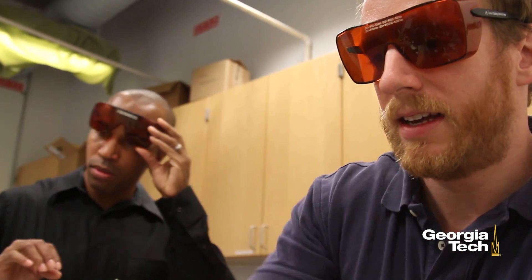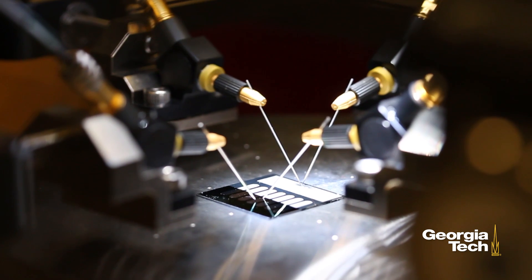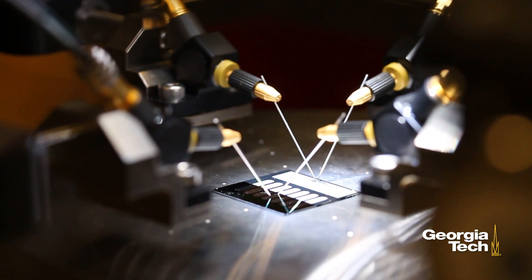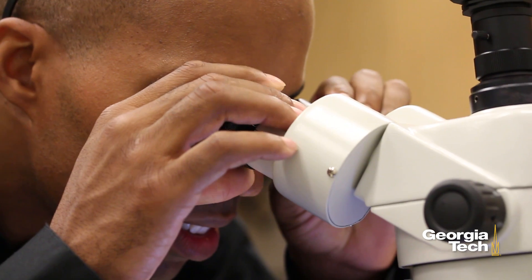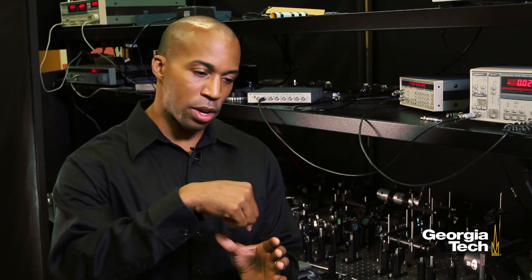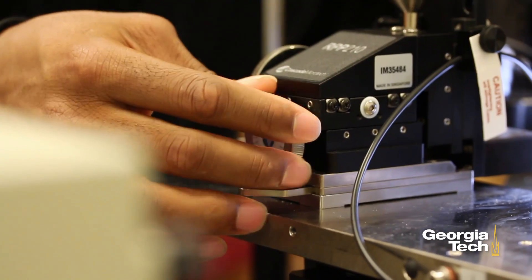which was part of the beauty of the discovery. You basically take any type of conductive substrate, and we can grow these carbon nanotubes like a carpet vertically off the substrate. We grow our nanotube, we conformally coat them with something that is an electrical insulator, and then we deposit another layer of metal on top to create a so-called metal-insulator-metal diode structure.